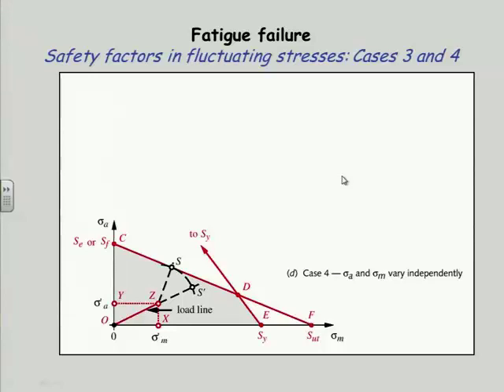So here I want to find what's the shortest way out. Well, the shortest way out of the envelope can be found by taking your compass, setting it there, and increasing the radius and drawing arcs until you find an arc that's tangent to the envelope, right? And that's the shortest distance out to the envelope. And I show that as point labeled S. And for a graphical solution, I could bring that arc from my compass down here until it intersects this line extended, which I've labeled S prime. And I could then measure, if I've drawn this to scale, the distance S prime to O and divide by the distance Z to O, and that would be my safety factor.